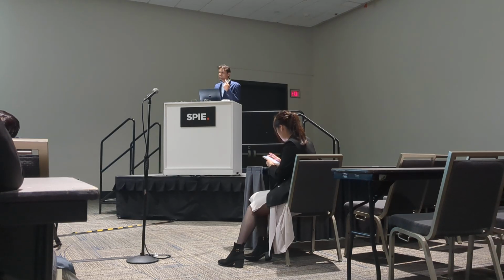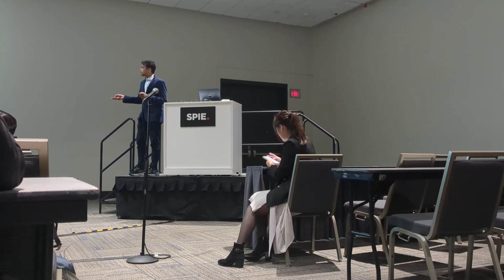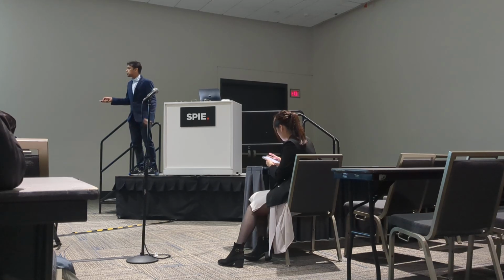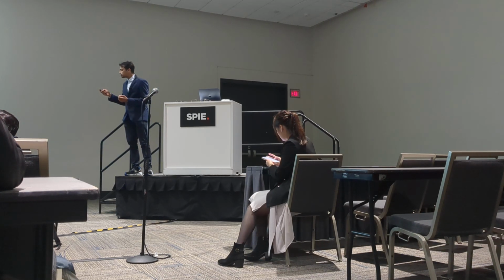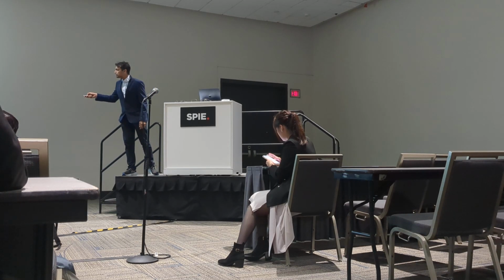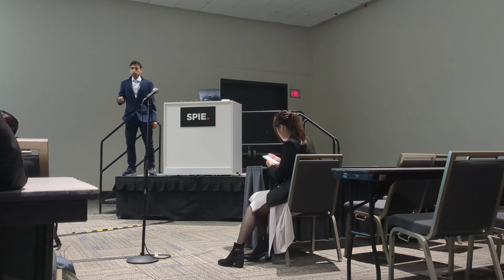One thing is that we need to have nanoparticles of gallium, and from the Fröhlich condition, a single-particle gallium nanodroplet in the dipole limit will have a plasmonic response around 8.9 electron volt. Then, to lower the response, we can encapsulate it in a medium of higher refractive index, let's say PDMS. But with that we can only come back to 7 electron volt.